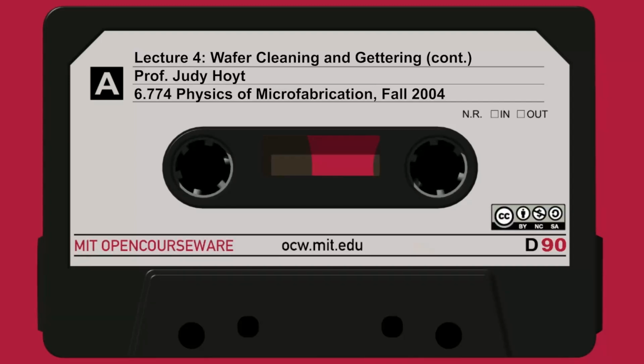You still have trace impurities, trace organics, and trace metals that got onto the wafer during the process step that you just did prior to this. So in order to remove those trace impurities, we do what's called the RCA clean. There are a lot of different variations on the RCA clean, but the one I'm outlining here is the most classic RCA clean. It typically has two major steps, one called Standard Clean 1, SC1, and one called Standard Clean 2.